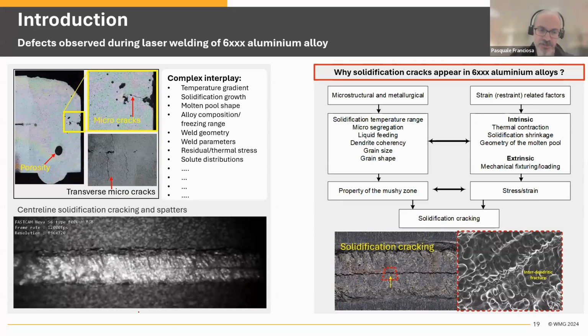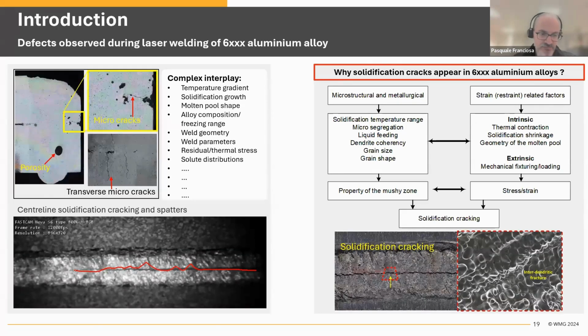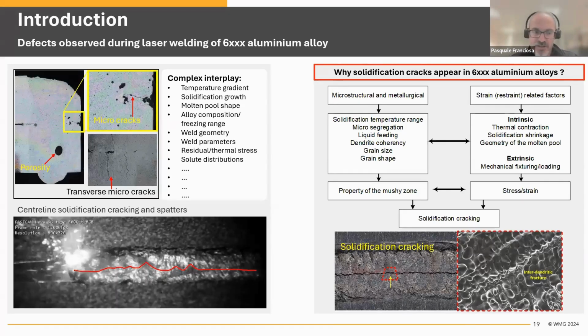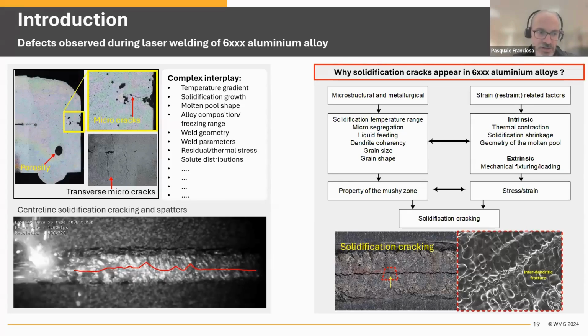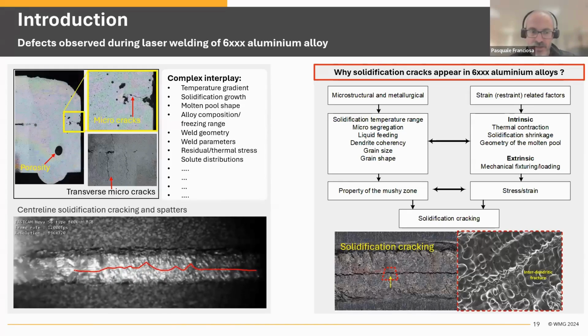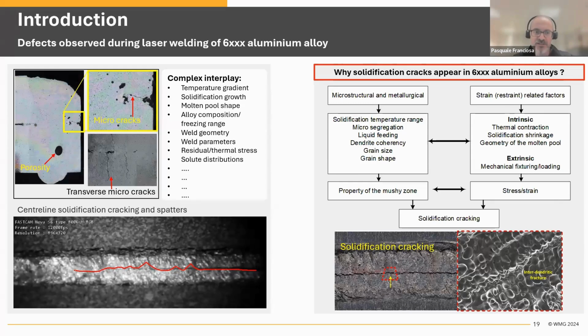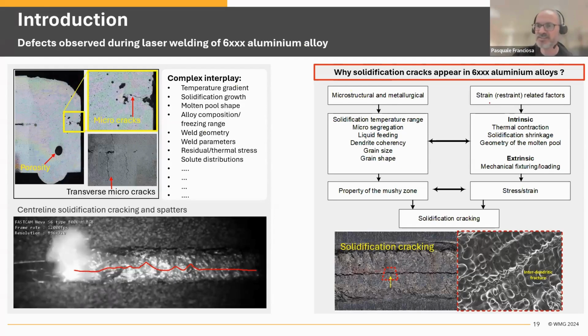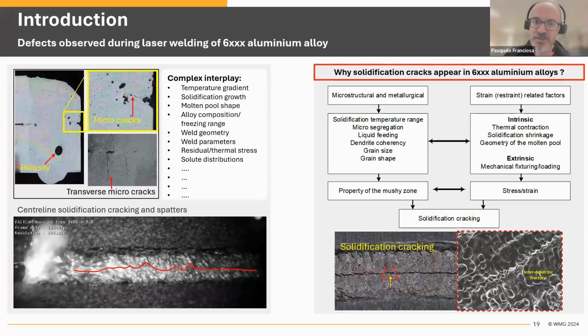And you can see from the high-speed video that the crack is forming just a few milliseconds after the laser has gone through the material. And when there are cracks, the weld is automatically not acceptable, so it's scrap. So the cracking process is quite complex. It's a complex interplay between different parameters and different physics involved. But in essence, it's a combination of microstructural and metallurgical elements together with stress and strain related elements.